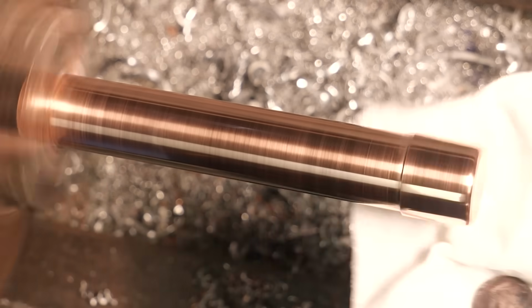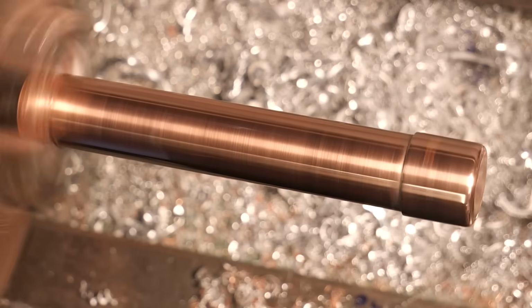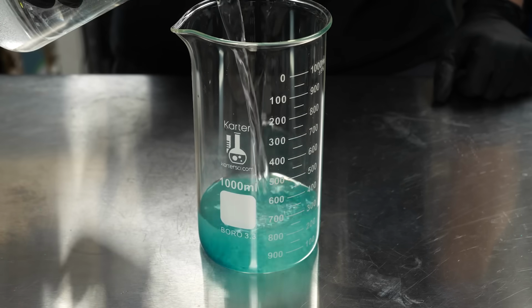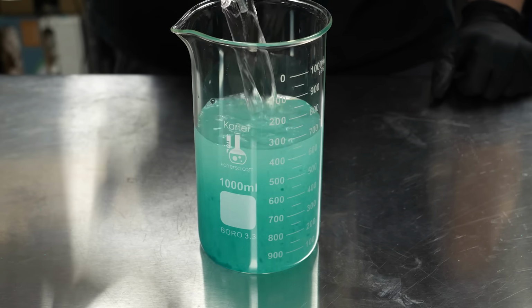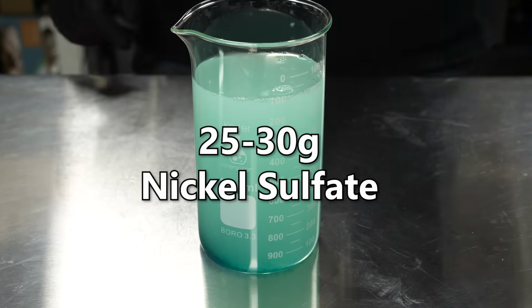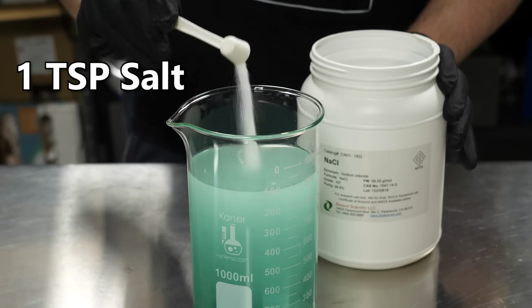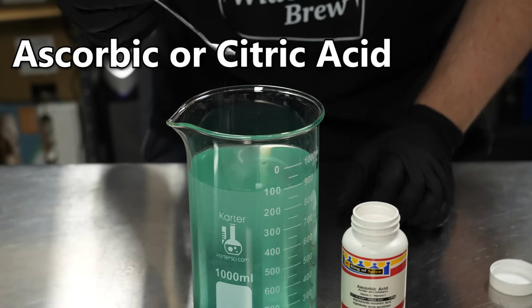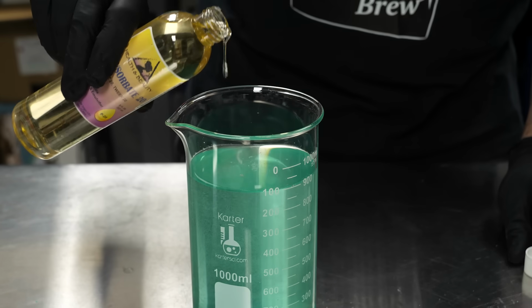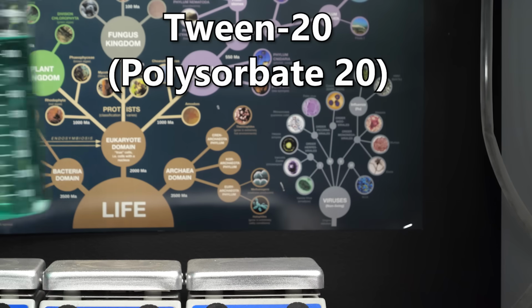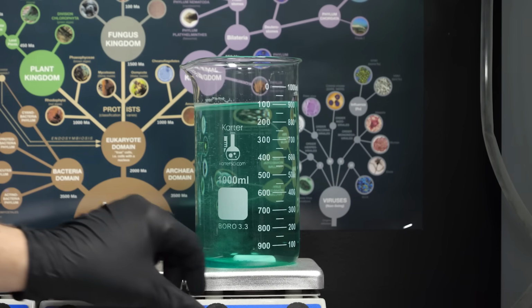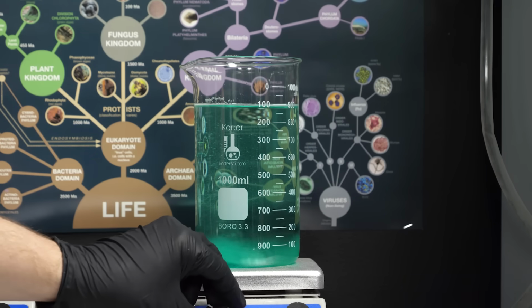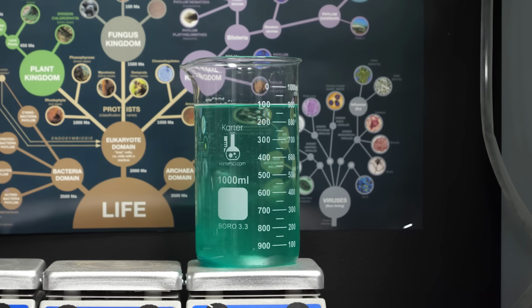Oh, and as you saw in the intro, we made a bunch of these things, so this process was repeated many times. In terms of plating, we whipped up a super fast, bright nickel plating bath. The ingredients are 25 grams of nickel sulfate, a teaspoon of salt, a sprinkle of either ascorbic or citric acid, and then a tiny bit of a surfactant. Here I'm using Tween 20, but a tiny drop of dish soap will likely work as well. We're not going for suds or foaming, we just need a little bit to break the surface tension.